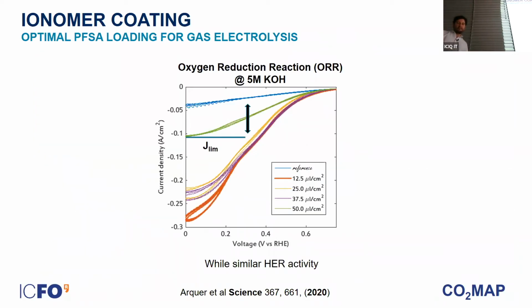And then we said, okay, let's see what happens when we put this into the electrochemical cell. And instead of working with CO2 reduction, we went into a simple benchmark reaction, which is the oxygen reduction reaction. We carried out this reaction in 5 molar KOH, in alkaline conditions, at different loadings. You can see here the reference as a blue line, and by increasing the loading of the ionomer in microliters per square centimeter, you can see how the limiting current density changes. When you see a plateau here, that means you don't have enough oxygen to be reduced. For example, in the green case, you start increasing the current density, so you are performing the reaction, and at some point this saturates.